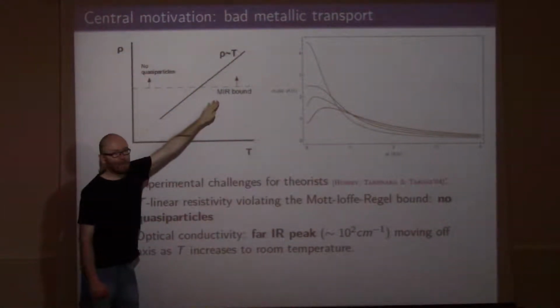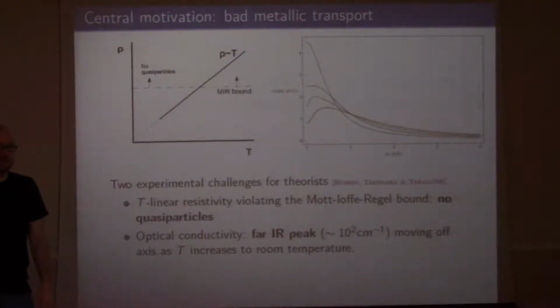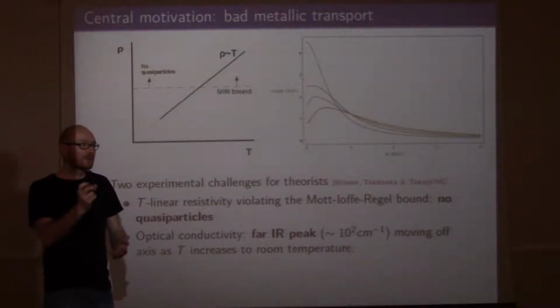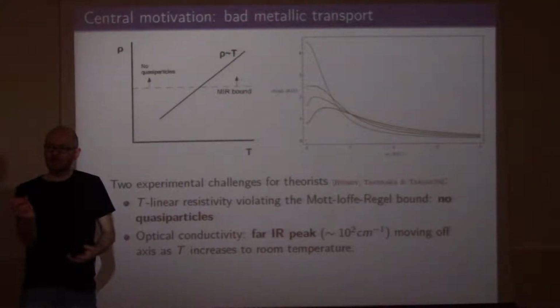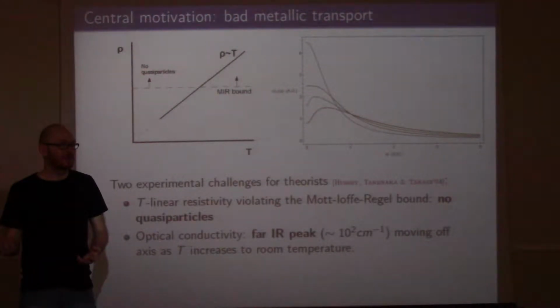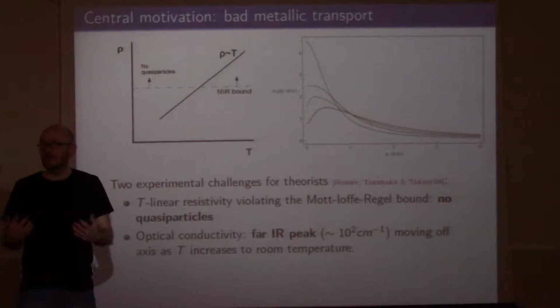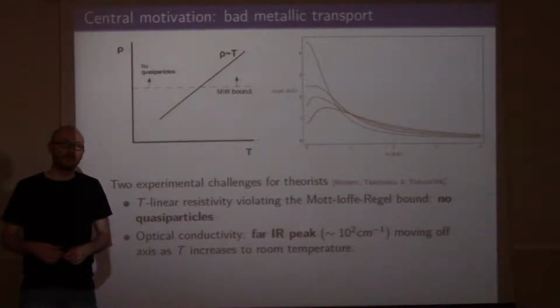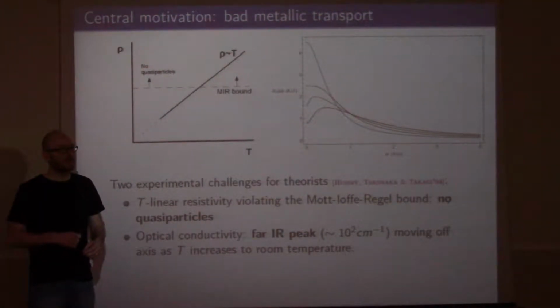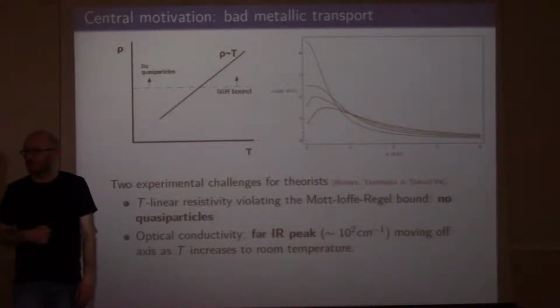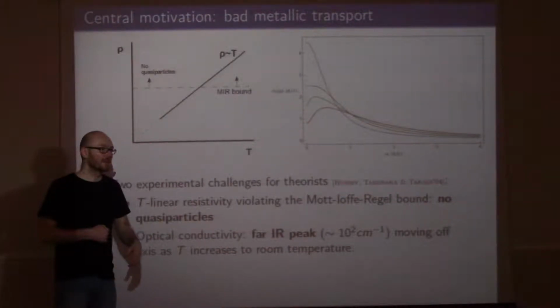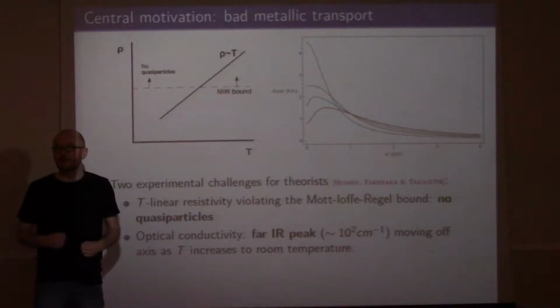There's this so-called Mott-Ioffe-Regel bound that applies to essentially all weakly coupled metals, and which is just a reformulation of the fact that since the elementary objects that are describing the low energy dynamics are quasi-particles, in order to even talk about quasi-particles, these objects should have a quantum wavelength which is smaller than the mean free path. Otherwise, you cannot describe them as coherent states. So this is related to some basically Heisenberg uncertainty principle between the quantum wavelength and the mean free path. So when you impose this inequality, you transcribe this in the computation of the resistivity, you find that the resistivity should be bounded from above by a certain value that depends, say, on the lattice spacing. It's not a very precise value, but at least it gives you some order of magnitude.